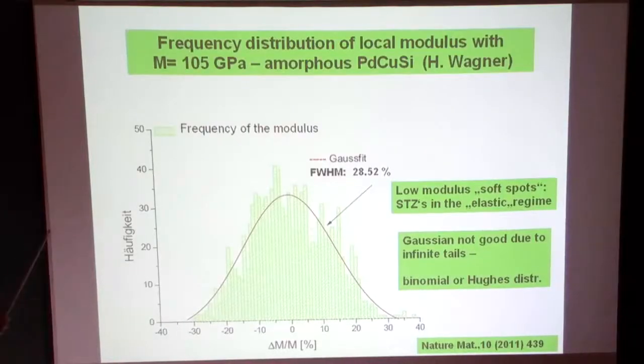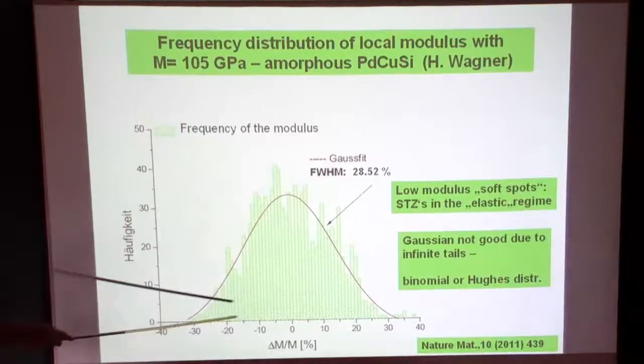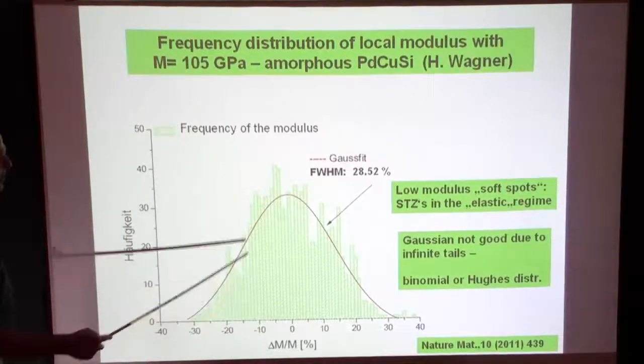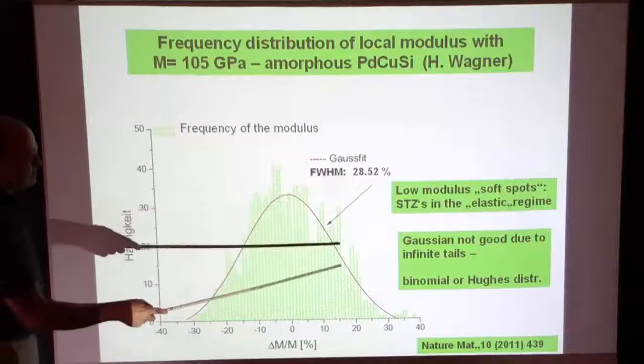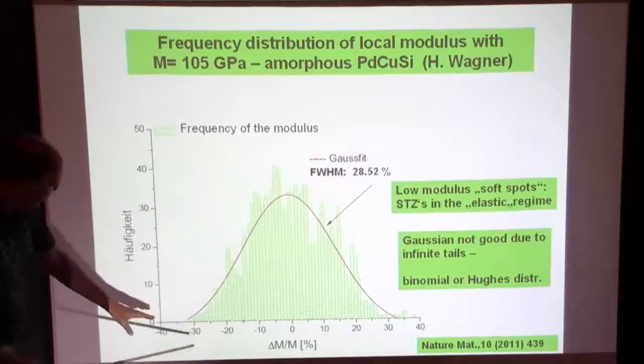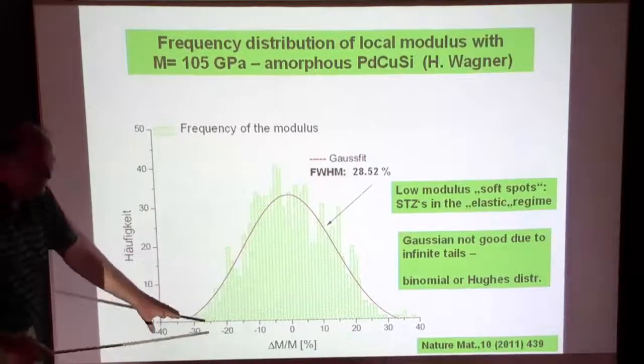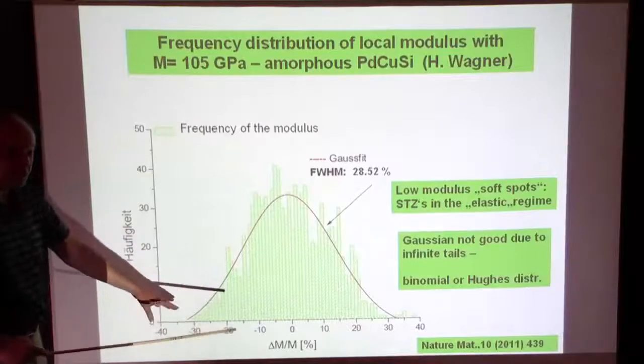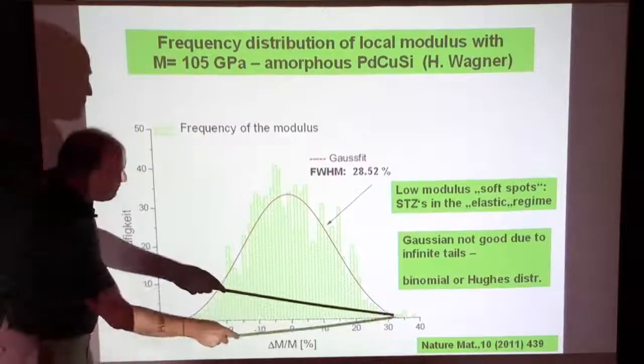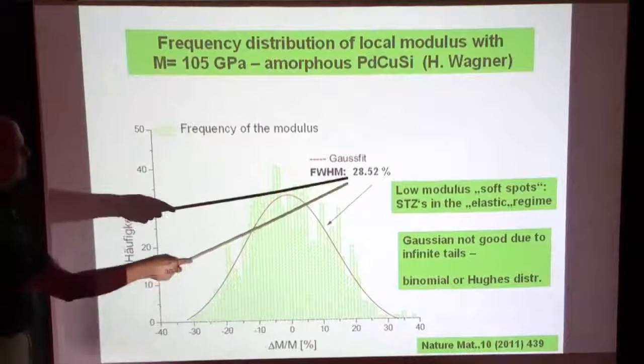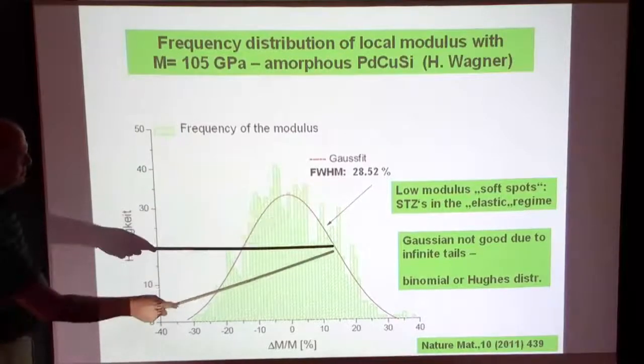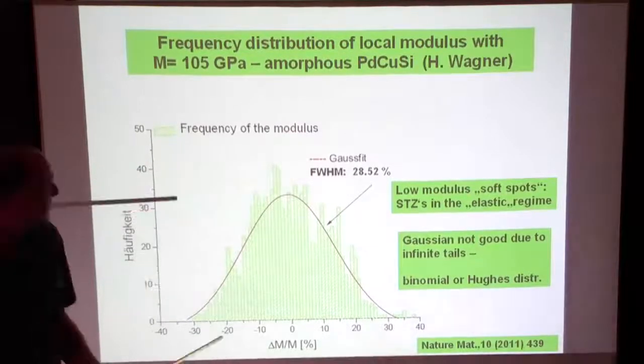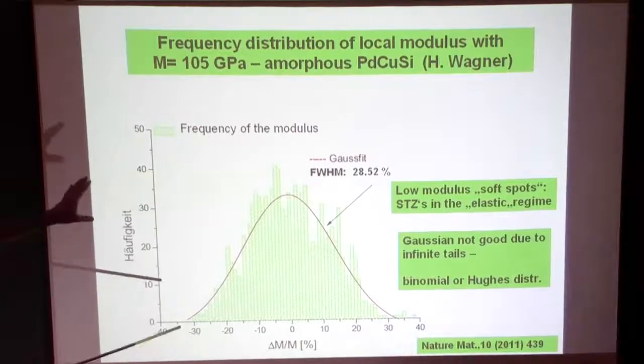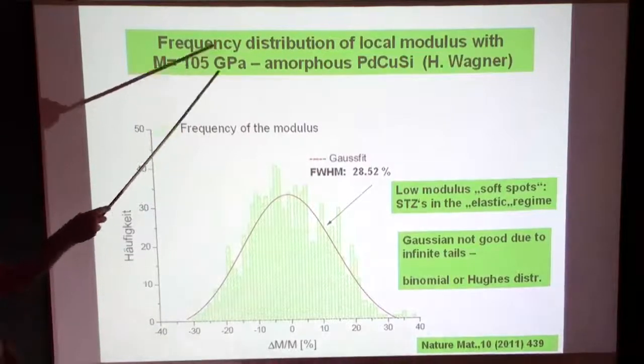Here's the numbers, okay. Now we plotted actually the frequency of the modulus which we measured over a mean value and fitted it to a Gaussian, which might be not quite true because we don't have the log plot here to get really nice ideas what it looks like, whether this is a Gaussian distribution in the landscape or not, but there might be differences. But look at the number, it's about 28% width. And this is 105 gigapascal.